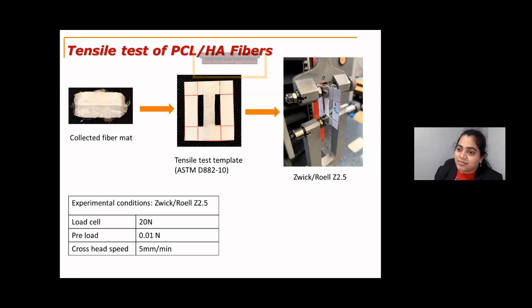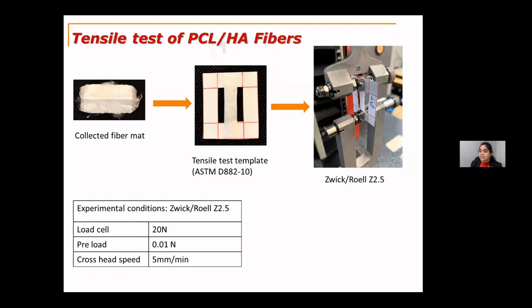Why was the true strain response not observed? Yes, that's a good question. However, tensile testing of fibers itself is not very consistent. Tensile testing depends on the orientation of the fibers. These fibers are just collected from the force spinning equipment, so they might be randomly oriented and not perfectly aligned. The orientation of the fibers also plays an important role in the tensile testing, which we neglect here. We are assuming that they are perfectly aligned. So that itself is not very consistent.